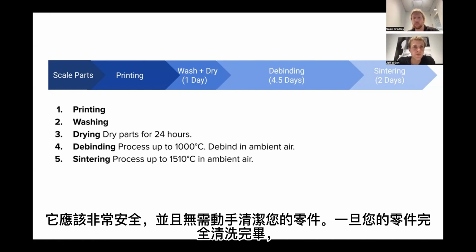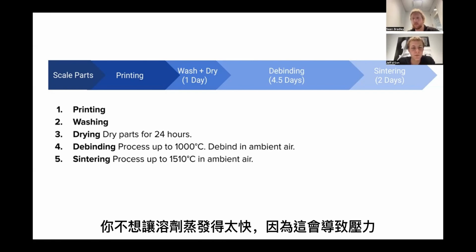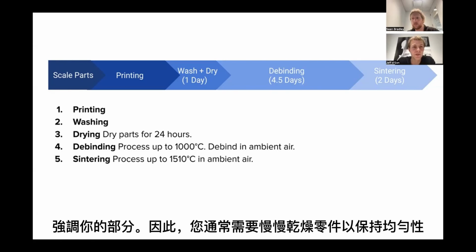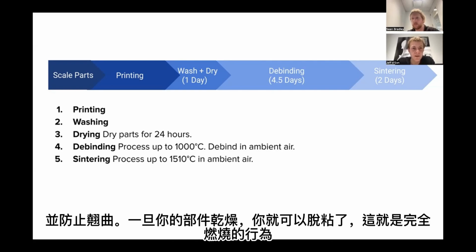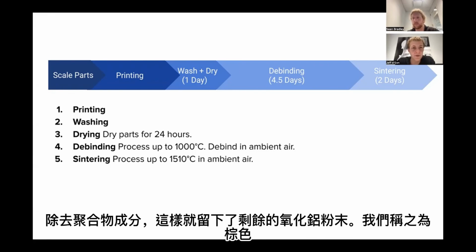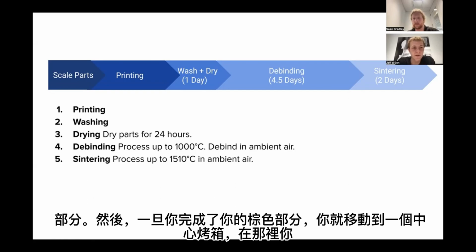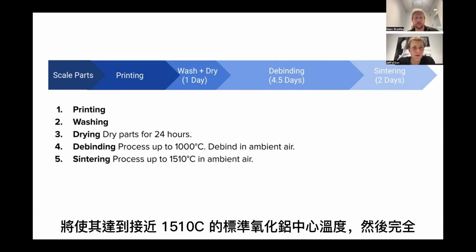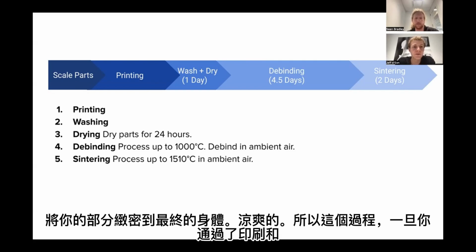Once your parts are fully washed, you don't want to evaporate the solvent too quickly because that would cause stresses along your part. So you typically want to slowly dry your part to keep the uniformity and prevent warping. Once your part is dry, you're ready to debind, and that's the act of fully burning out the polymer component so that you're left with your alumina powder left over. We call that a brown part. And then once you finish your brown part, you move over to a sintering oven where you would bring it up to standard alumina sintering temperatures, close to 1510 C, and then fully densify your part into the final body.